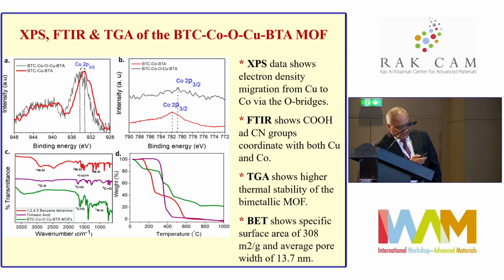You can also look at the FTIR and see that the coordination in the bimetallic system with both the carboxylic acid and the CN groups shifts to higher frequency. And this is shown here, which indicates, again, better coordination between the cobalt and copper and the organic linkers here. In the TGA analysis, we see also in the bimetallic there is a shift to higher thermal stability. This is the green pattern here. There are 5 different steps of weight loss, but in all they have much higher stability than each of the individual monometallic MOF.